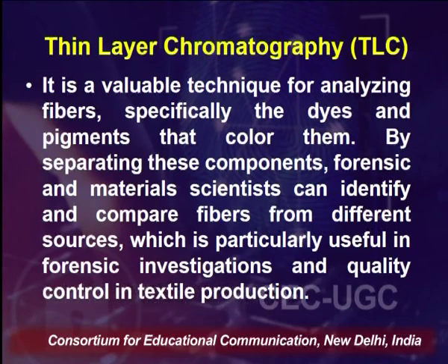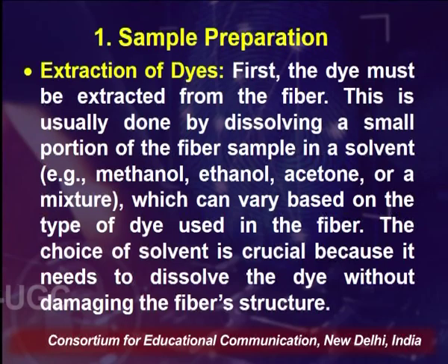There are different steps which we follow in TLC. The first step is extraction of dye. We can use a combination of chemicals, for example methanol, ethanol, acetone, or a mixture of any solvents. The dye can be dissolved using these solvents, and this does not damage the fiber structure. We will take a drop of this mixture and then load this sample on a TLC